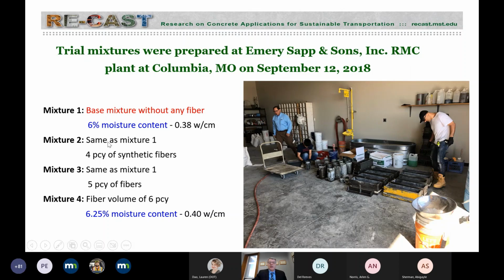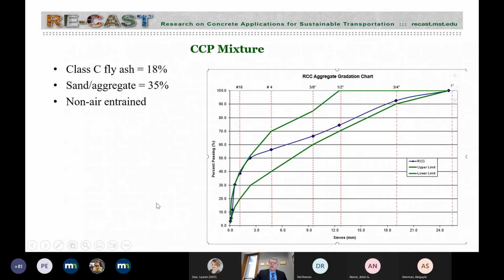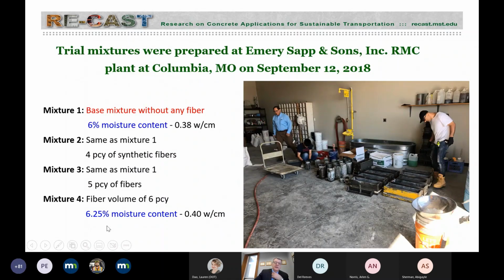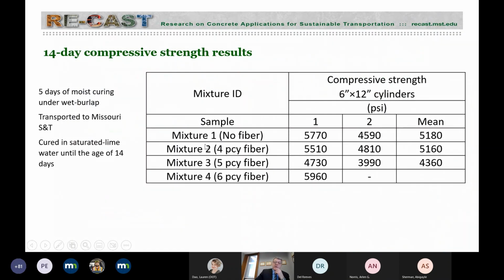And the second one, in consultation with Euclid Chemicals, we opted to start with 4 pounds per cubic yard based on experience with concrete pavement, but concrete pavement was 1.5 to 2 inches in consistency. This is zero slump, as you know. And then we went to 5 pounds, and then went to 6 pounds, but we found out that the mixture was extremely dry, and then we had to increase the water content a little bit. So 6.5%, 6.25% moisture content. The final option was to opt for mixture number 3. I'll show you why.